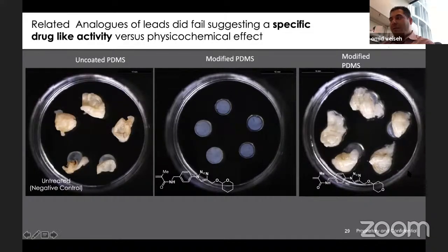And what's fascinating about this is that these two molecules actually have the exact same physical properties because they have an identical number of oxygens, nitrogens, and carbons, but it's just the specific molecule activity that's giving rise to this impressive response that we see, similar to how drugs work. So an analog of it failed essentially. And all we had to do to break it is just move one oxygen group, and the whole thing lost all activity. So it's pretty exciting that we stumbled upon the ones that worked, kind of fortuitous in a sense, because it seems to be very specific ones that give you these impressive results.